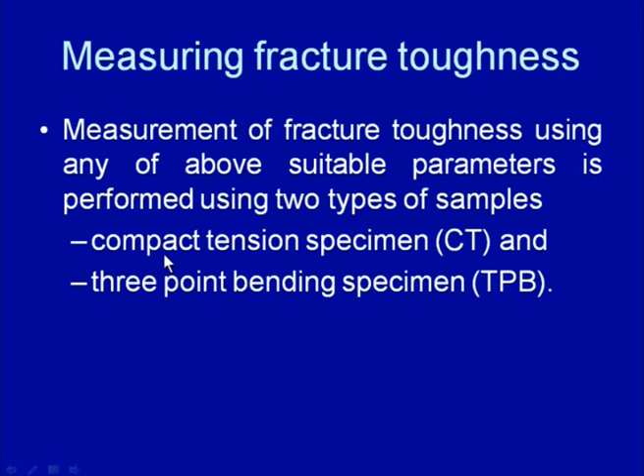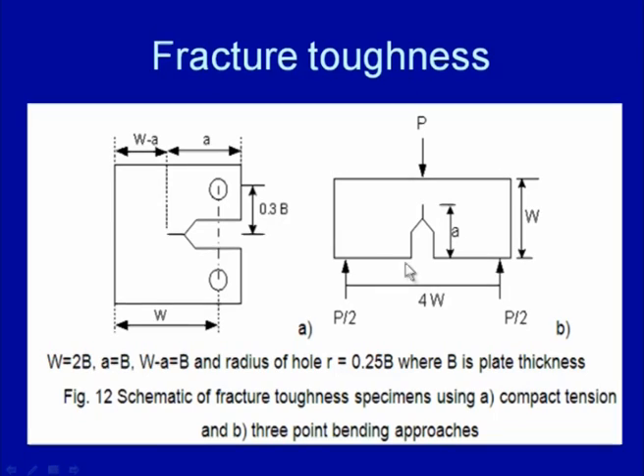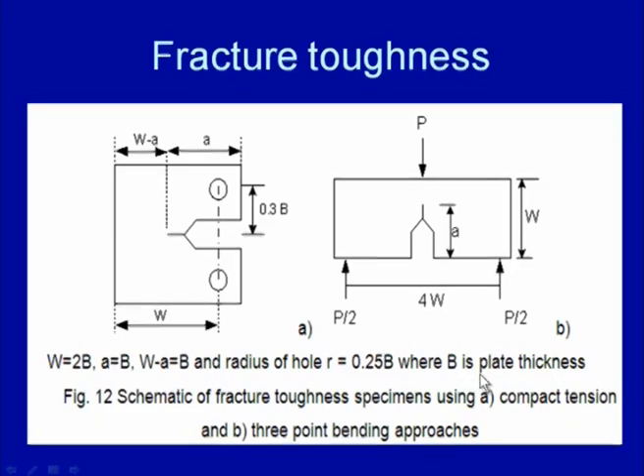For measurement of the fracture toughness, two types of specimens are used. One is the compact tension specimen, commonly known as the CT specimen, or the 3-point bending specimen, abbreviated as TPB. These are the standard samples and the different dimensions have been shown here. Here B is the plate thickness. We always start with the plate thickness for fracture toughness, because it plays a big role in determining which type of test is to be conducted.